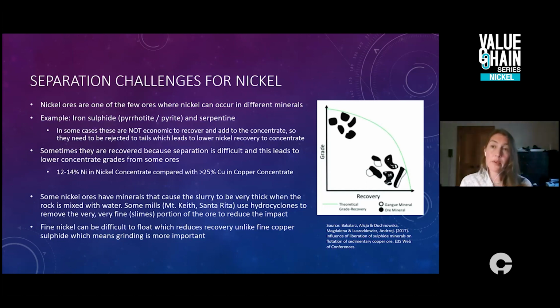And sometimes, however, we specifically look at nickel, more traditional nickel sulfide deposits that have a significant portion of iron sulfides, which are called pyrrhotite or pyrite. Traditionally, a lot of those materials would be recovered to the concentrate, and it would increase the nickel recovery overall. However, it would lower the concentrate grades.